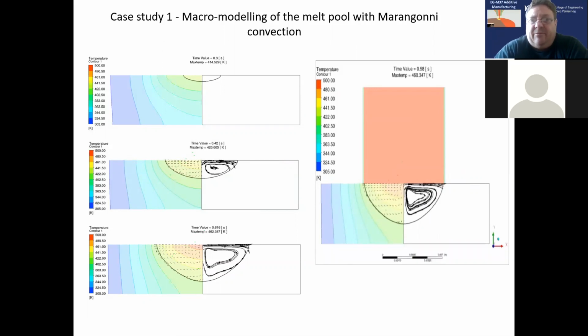Now, this is driven completely in the modeling by the surface tension at the interface between the solid and the liquid. And this surface tension causes a flow in this direction, which actually causes a wider rather than a narrower melt pool to develop underneath the laser. So you can see the melting is coming out. This is actually going to go wider than the diameter of the spot coming down on it. What would have happened if the surface tension had caused the melt pool to go in the other direction? So let's put that out there as a question.